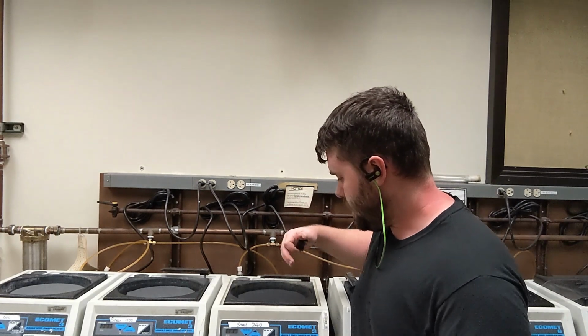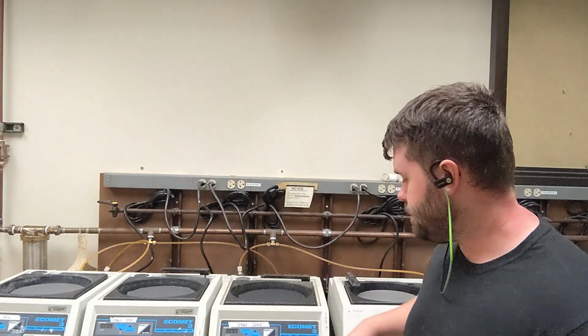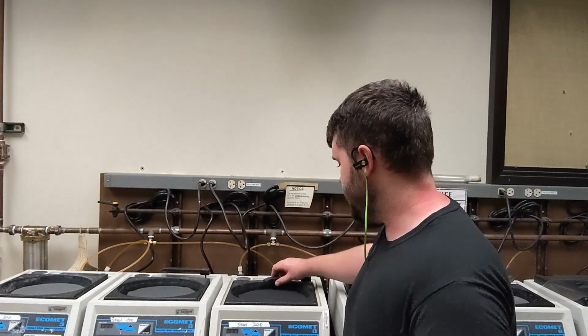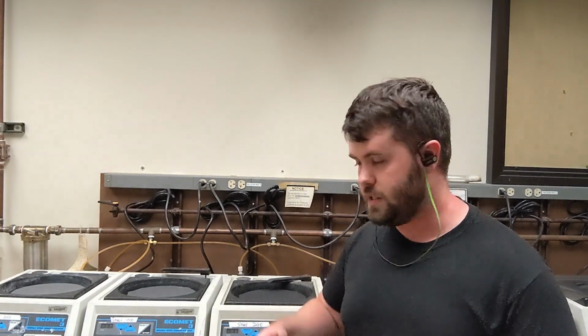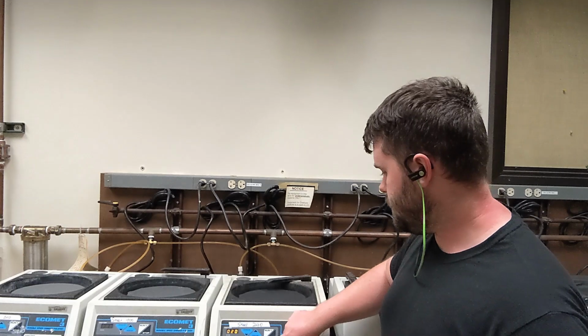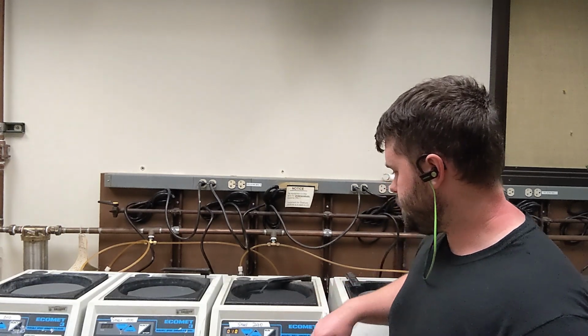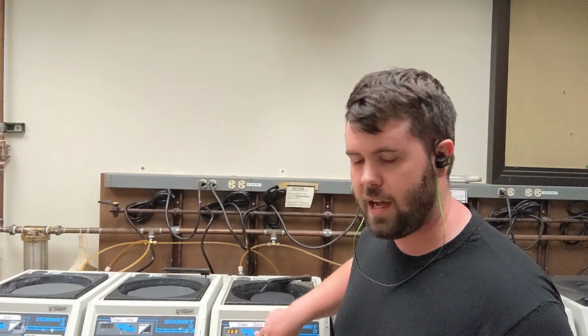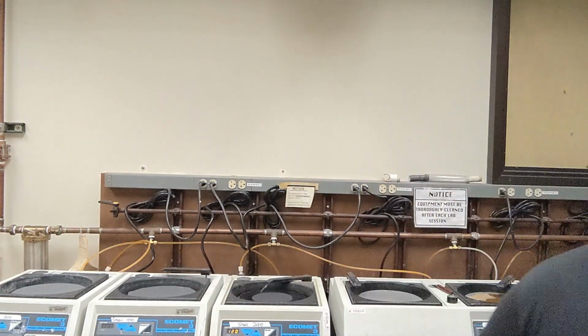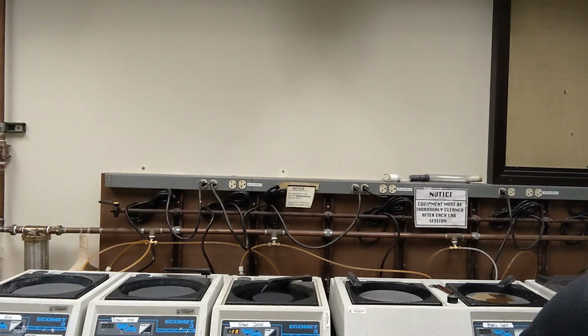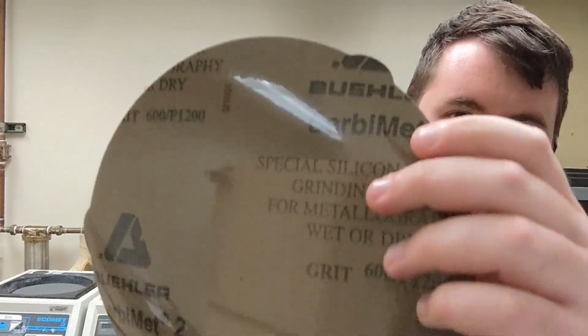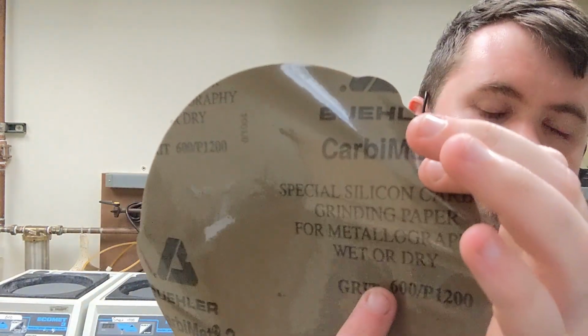Each of these is fairly easy to operate. There's an on-off switch, there is an RPM setting, and there is a water setting. These use water to carry off the debris as you polish the sample, so the sandpaper lasts longer. The sandpaper is just sandpaper like this, and on the back is written the number we care about, which is the grit number.